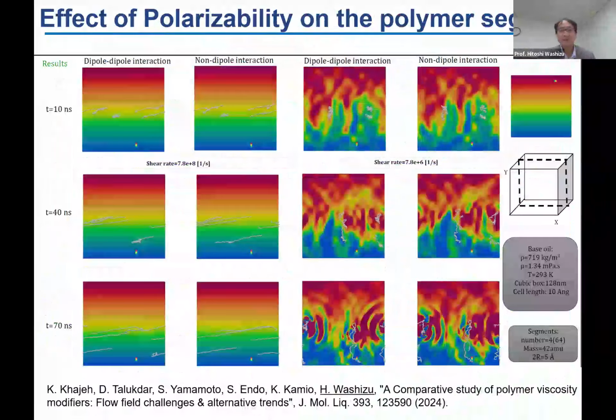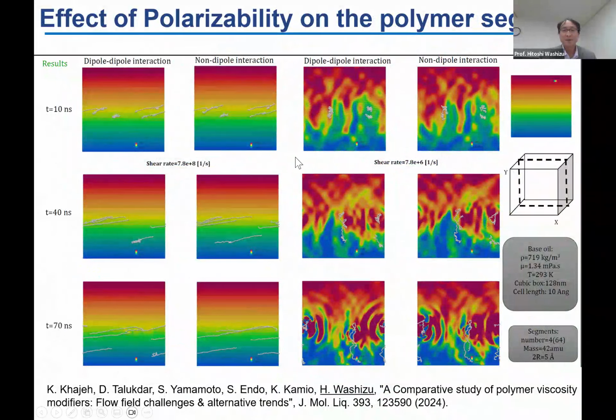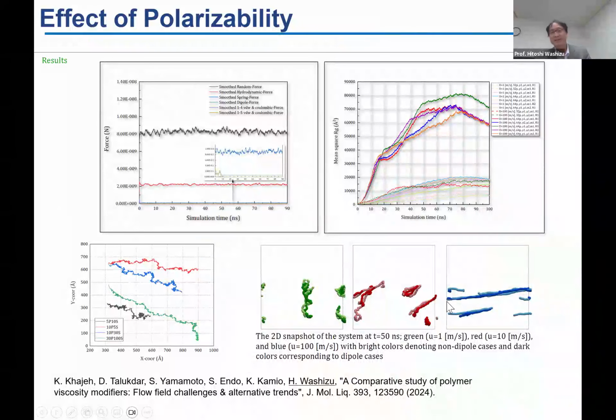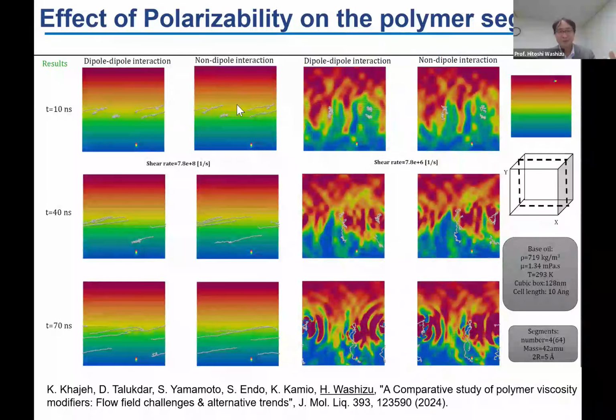Okay, there are many applications, but we introduced some effect of charges, and this is the difference between the dipole and non-dipole model. And then the structure of the polymer changes. This means that we can make much more precise chemistry in this model. So this is very good. We are collaborating with a chemical company, Mitsui Kagaku, and we could explain which kind of friction modifier polymers are good for the dipole, I mean the polar system, and the non-polar system.